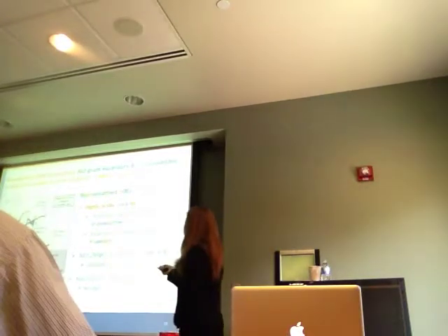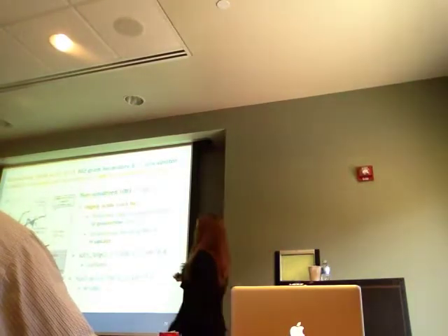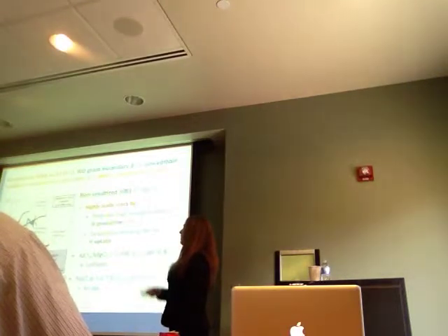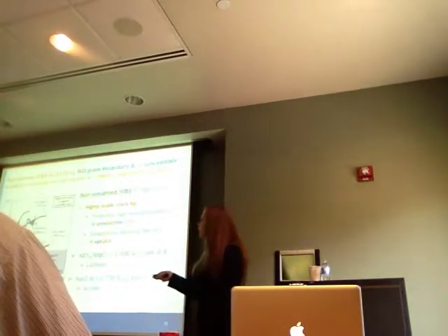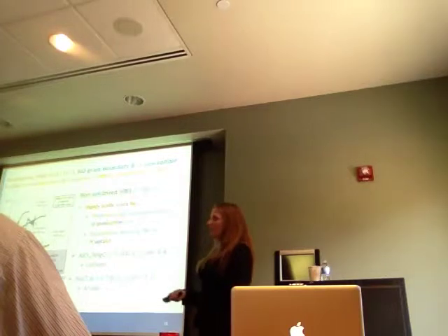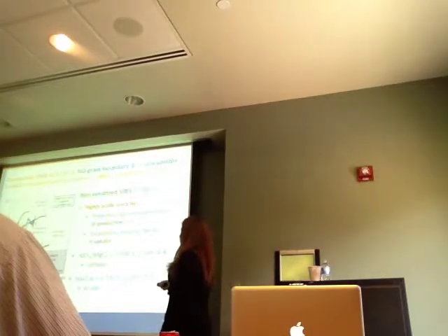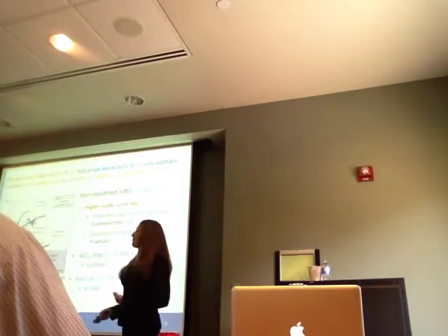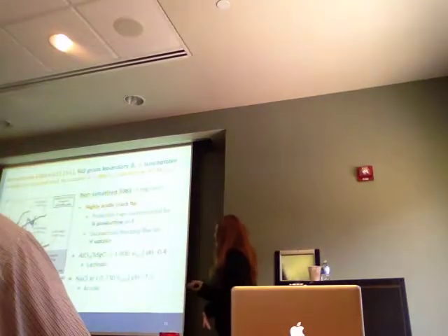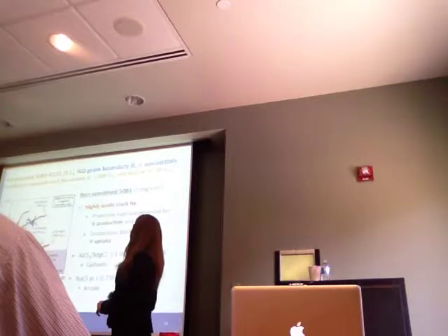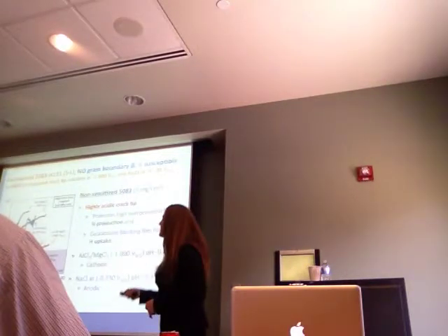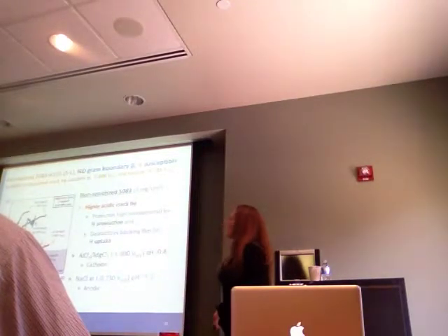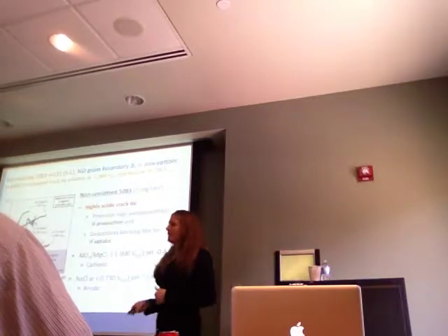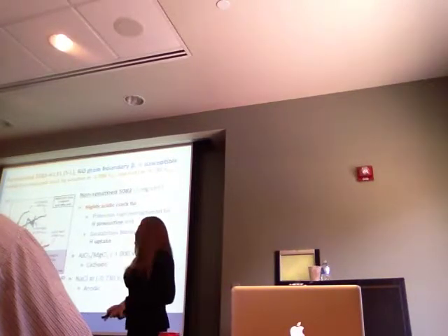Now we cathodically polarized this solution and we still saw very high crack growth rates and very low threshold stress intensity. We also ran an experiment in sodium chloride at an anodic polarization, negative 0.73 volts at a neutral pH. And this anodic polarization drove the dissolution of the matrix. So you also see nice cracking, again at relatively high crack growth rates, well above the resolution limit.